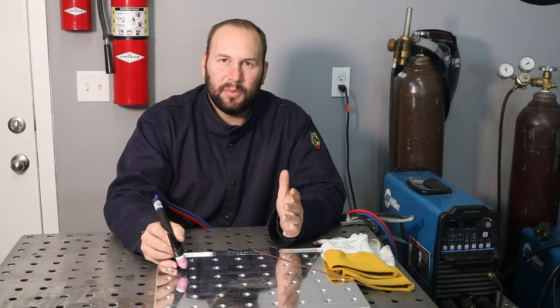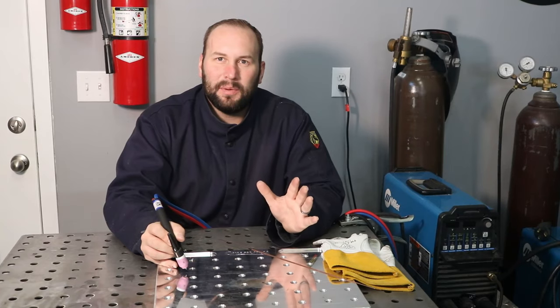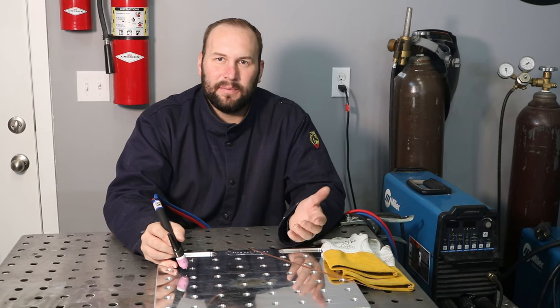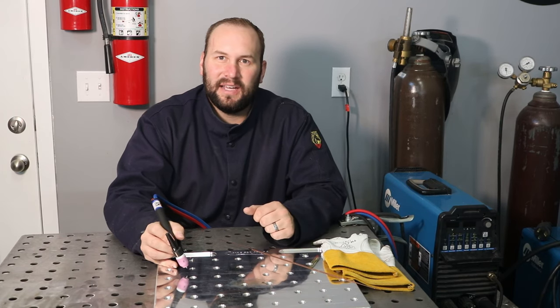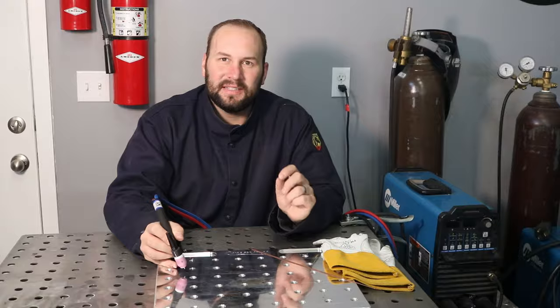Just to show you what that should look like, you're welding along here and you just dab that filler metal right into the leading edge of the puddle. And that works pretty well. But here's what you're probably going to see, or at least something I experienced and most people that I've taught have experienced: you can see the end of that filler metal is balling up and then just flopping in as liquid into the puddle. Now you don't want that.